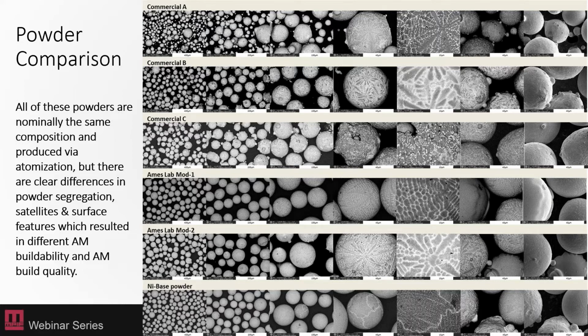These are from 3 different commercial suppliers, as well as 2 powders produced in-house on the Ames Laboratory systems, as well as a PREP produced powder on the bottom there. And you can see how there are different solidification features on the surfaces of the powders, different dendrite sizes. The white features on these surfaces are carbides, and so even just the carbon contamination and carbon level is different within these powders. Again, they were supposed to have some carbon in them, but the level is clearly different across the different suppliers